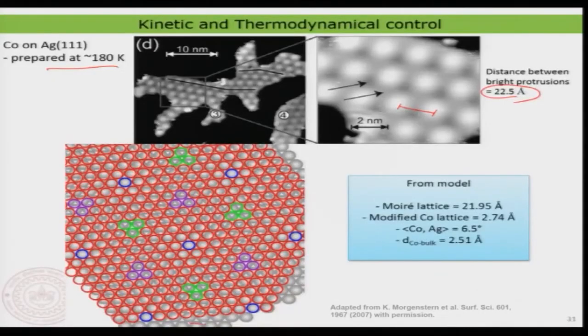Now, what I have to do in this exercise is to regenerate a model for the microscopic arrangement of the atoms, the atomic arrangement at the interface. We also need to keep in mind that in this particular case, the cobalt lattice and the silver 111 lattice are oriented by 6.5 degrees. So let us do that. Now you can see this is my silver lattice, and here you can see the cobalt lattice is basically going in this way. So that means there is an angle between them of about 6.5 degrees. So there is an orientation.